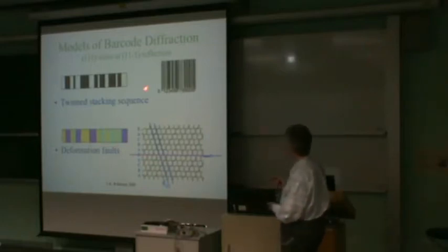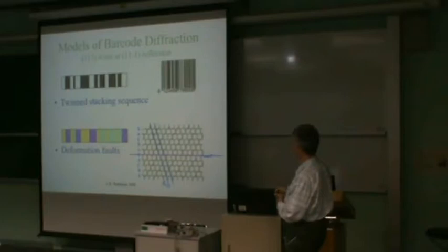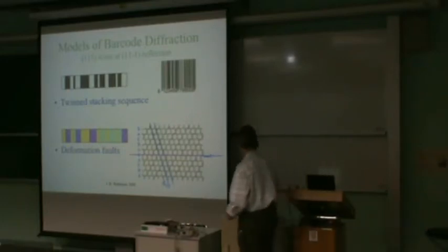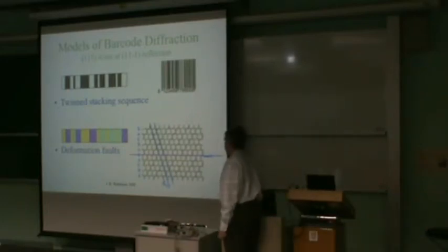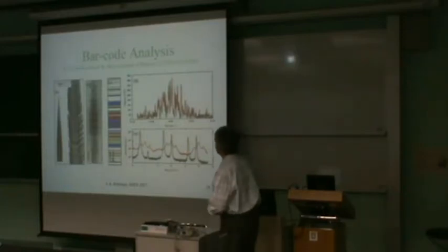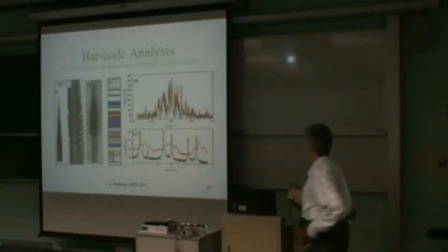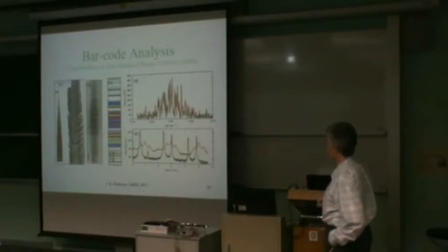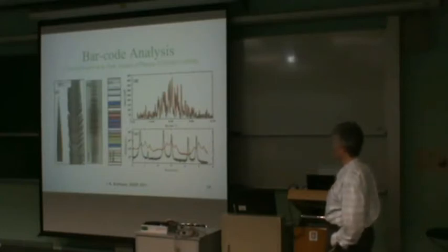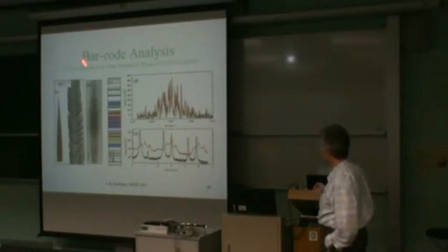And it's not the same as what you would get by light-dark contrast, which would correspond to a more traditional kind of barcode. What Vincent has done here is model both kinds of stacking faults, and he's got a genetic algorithm that gives a relatively good agreement with the data, but unfortunately it's not a unique image. So what we've got here are stacking faults.